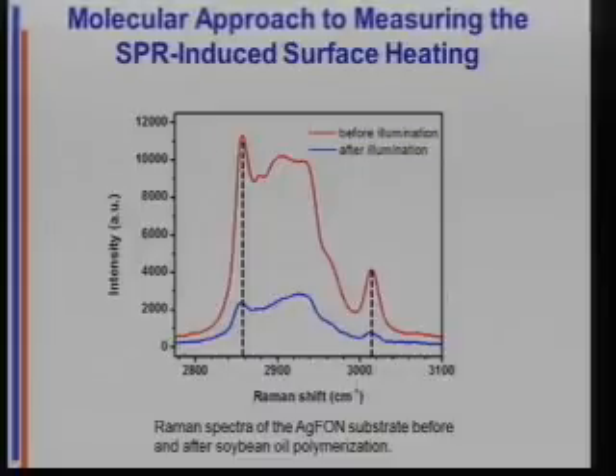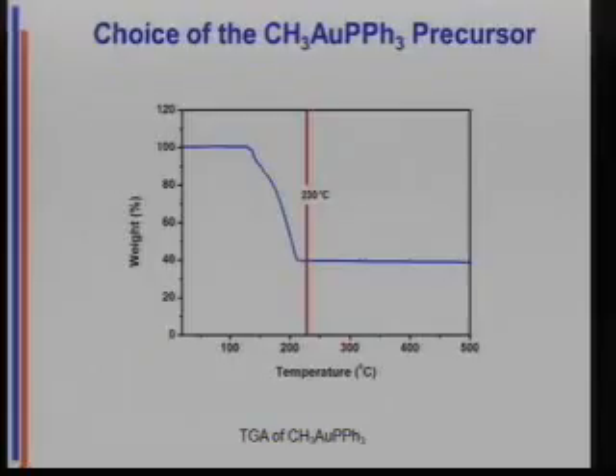So the answer is the hotspots are at least 230 C. So now I have a temperature range to work with. And so this is the TGA, the thermogravimetric analysis of this particular compound, methyl gold triphenylphosphine. Okay? And so what I'm doing is I'm following the mass of the sample versus temperature. This plunges around here. This is 230 degrees C. This is my barrier. Okay?